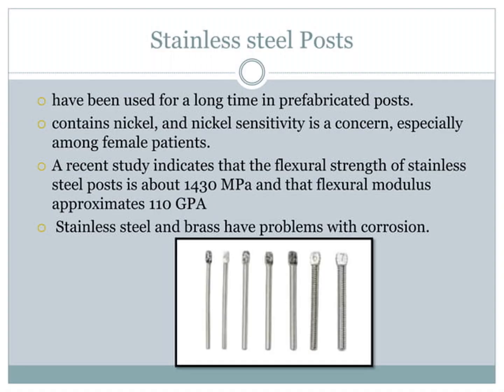Metallic posts. Stainless steel posts have been used for a long time and prefabricated posts contain nickel. Nickel sensitivity is a concern, especially among the female patient. A recent study indicates that the flexural strength of a stainless steel post is about 1430 megapascal and the flexural modulus is approximately 110 GPa. And stainless steel and brass have problems with corrosion.